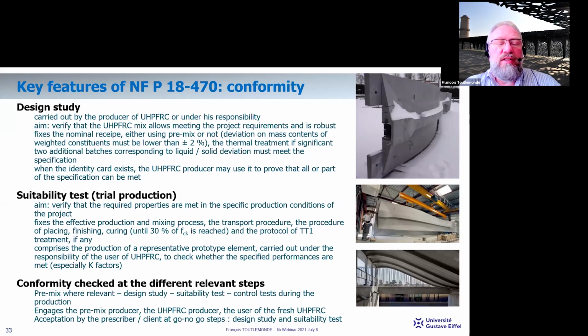When there is an identity card, this may replace the design study. But a key step not so classical for concrete in general is the suitability test, part of the initial testing, which is in fact a trial production. Its aim is to verify that the required properties are met under the specific production conditions of the project, and it fixes the effective production and mixing process, the transport procedure, placing, finishing, curing, and the protocol of thermal treatment if any.